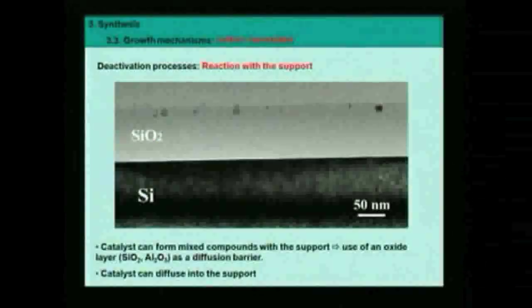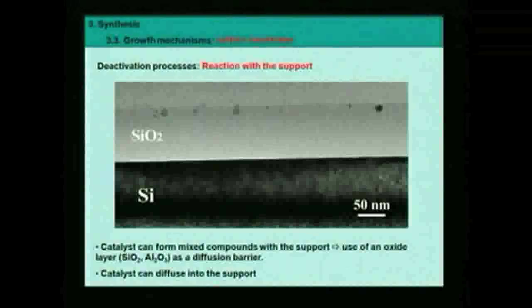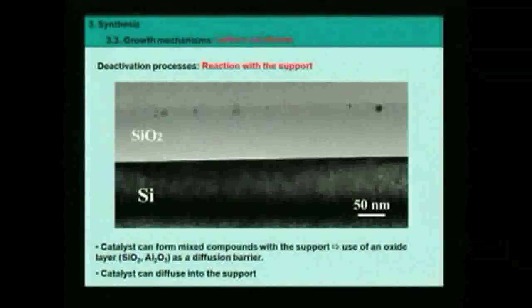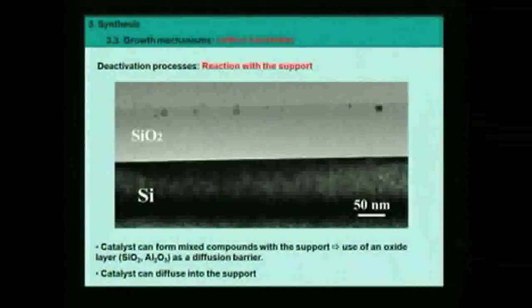Okay, another deactivation process is reaction with the support. So I already mentioned that you can form alloy compounds like silicides when you put a metal like iron or nickel on silicon and you heat it, then you will very quickly form iron silicides or nickel silicides because it's a very stable compound. To prevent that, because silicides are not good catalysts, you need to use a barrier like an oxide. Oxide is much less reactive than the silicon, and if you use a silicon oxide, you can prevent the reaction between the metal and the silicon and prevent the formation of silicides, for instance.